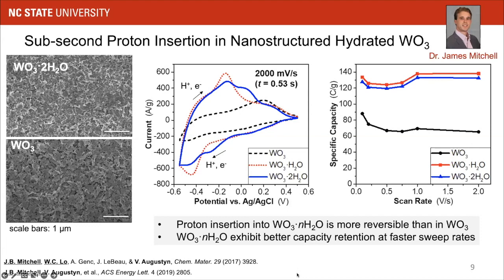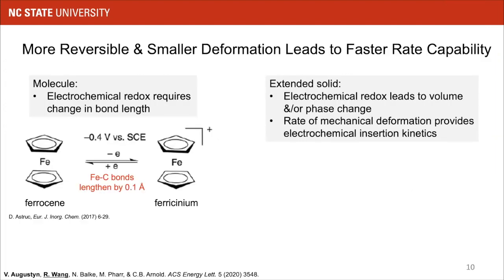Because of the thin film nature of these electrodes, we could push them at extremely fast rates. So this is a cyclic voltammogram at 2000 millivolts per second. And we saw that at these rates, the hydrous materials were performing better than the anhydrous material. This was previously observed in the literature and attributed to this Grotthuss transport property of hydrous tungsten oxides. What we found, though, was something a little bit different.